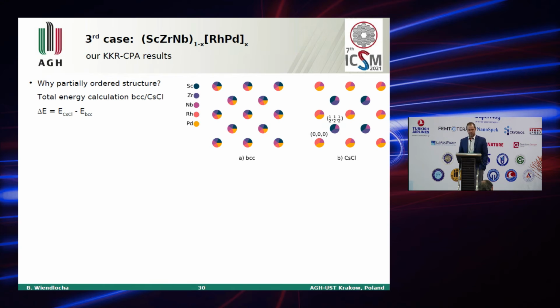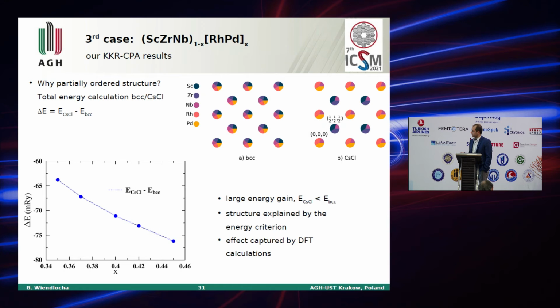So we wanted to see whether we are also able to explain that in calculations. We started with the question of why this partial ordering takes place in this system. So we compared total energies of the random alloy and this cesium chloride structure, and the simple energy criterion looks like it's enough to explain. Energy is simply lower if the system adopts this cesium chloride structure.